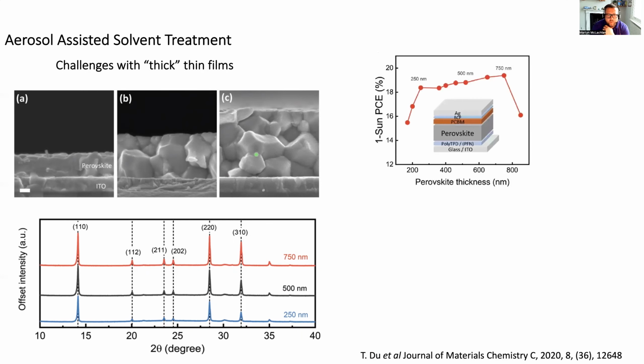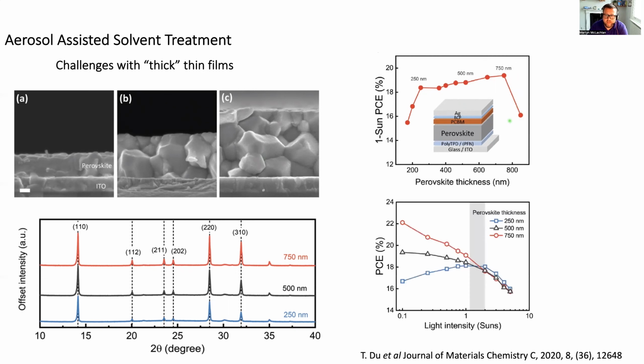The reason I mention this is we have a limit in terms of the thickness of the films that can be processed, but we see this really quite nice increase in performance as we increase film thicknesses that begins to tail off quite rapidly, where we believe that the in-plane grain boundaries that exist are having a detrimental effect on film performance.